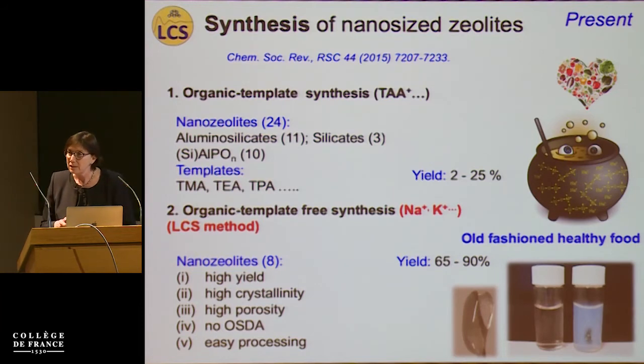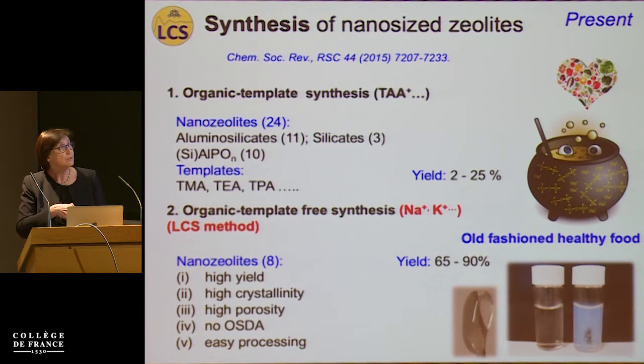The classical methods for preparation of nano-size zeolites rely on the use of organic structure-directing agents. Using tetraalkyl ammonium cations, such as tetramethyl, tetraethyl, tetrapropyl ammonium hydroxide, we are able to synthesize 24 nano-zeolites. But a big disadvantage is the very low crystalline yield, which is in the range of 2–25 weight%.